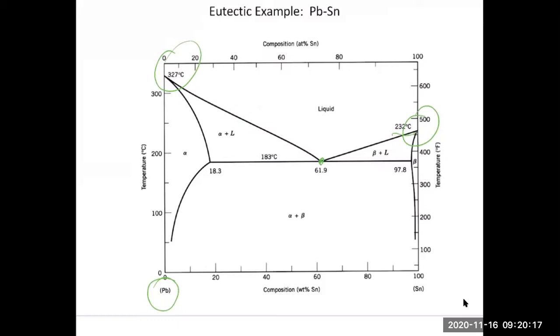Unfortunately, this was the best one. So basically now people use mixtures, still tin-based, but they typically add things like silver or copper, antimony, bismuth, basically a bunch of other things. But unfortunately, nobody's gotten it down as low as 183. So commercial solder now is a little higher, but we've gotten rid of lead, which is good.